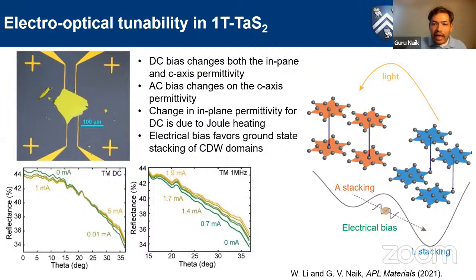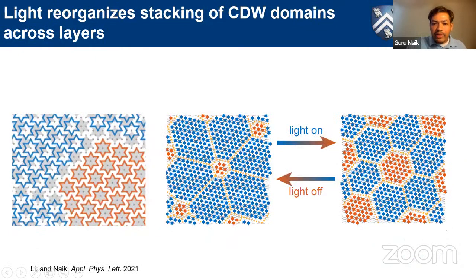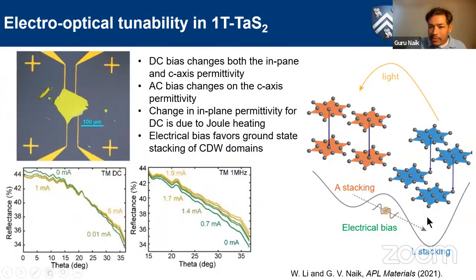So again, I think I haven't discussed all the things here, but in this analysis, we also have a few other simple electrical resistance measurements as a function of illumination intensity, etc. But the summary of all our analysis is shown here. With an electrical bias, what happens is the ground state stacking is more preferred. And just the same thing that we had in the previous case, we have both of these blue and red stacking domains showing up in our material. But as we now bias this, the blue domains increase in size and red domains shrink in size. So that's contrary to how it happened with light. So electrical bias pushes this way, light pushes the other way. So that's what we came up with.